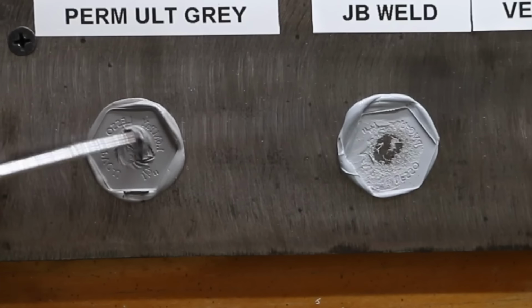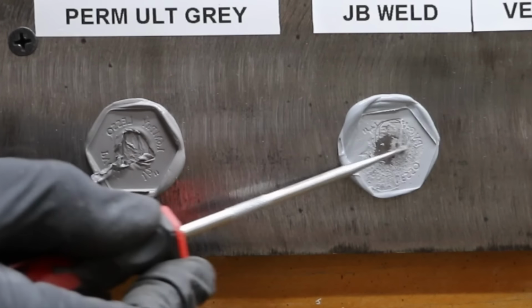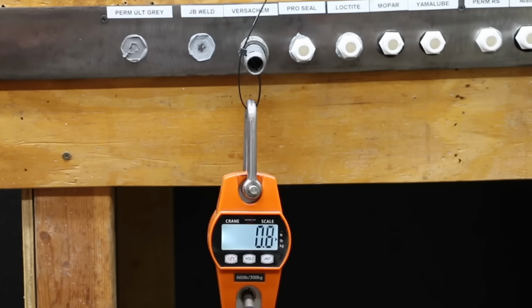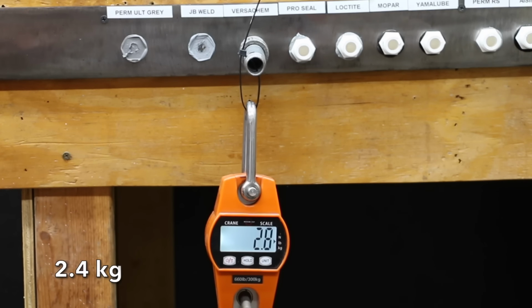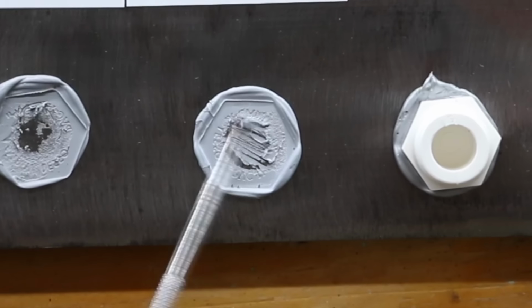Just like before, the Permatex and the JB Weld did not fully cure in the center of the test pieces even after 72 hours. Just like the JB Weld, the Versachem seems to have pretty good flexibility and made it to 5.2 pounds before slowly letting go.